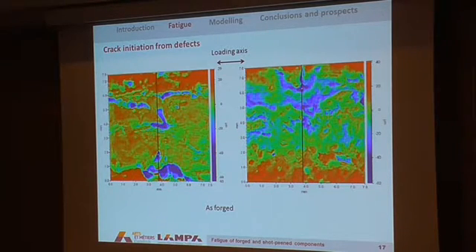So we're able to find, among all the defects, which one is responsible for the crack. And if you look at these two pictures, you see that it's not easy to find which defects would be responsible for a crack initiation. And I can tell you that the crack initiates here and here.